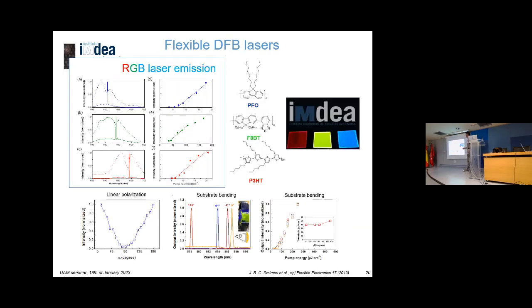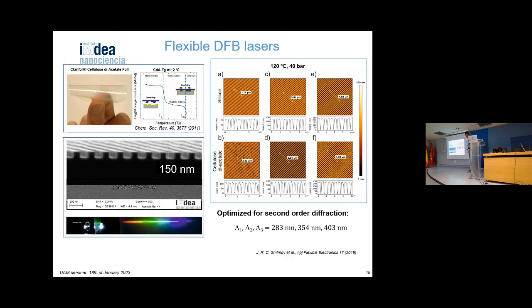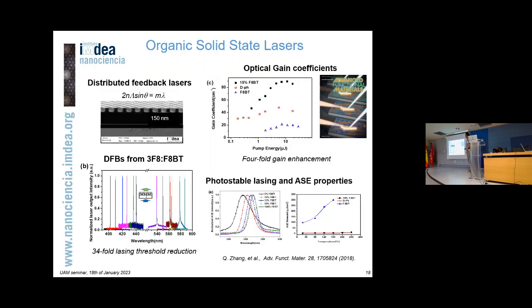Essentially, we know where our systems emit, and we know where the stimulated emission is located. So if you go to the Bragg law, which is not written here, sorry, here it is: you know lambda, m is the diffraction order that you want to plot, 1, 2, whatever. Typically what you want is the diffraction along the plane, because you want basically to confine the emission in your cavity. Your cavity is your film, on top of this sort of mirror.